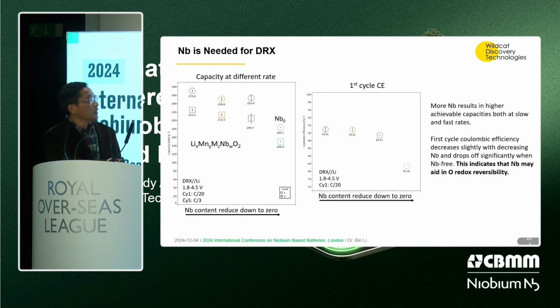Here's a little more detailed example showing that even when you go to niobium 0, the difference in capacity is huge. Niobium plays a very important role. Even if you just look at cycle 1 coulombic efficiency, without niobium you only get 81%. With niobium, you can get 90%, which is enough as cathode materials. So again, there's a lot of work that can be done by academic research to understand why.